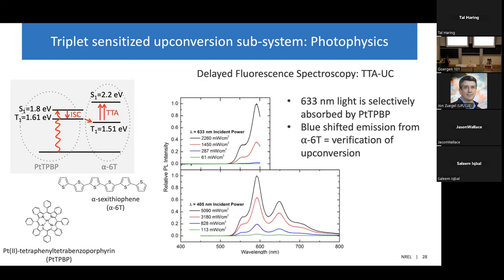All right. So after proving that we're populating the triplet levels of alpha-6T, we need to show that upconversion is actually happening. And for that, we turn to delayed fluorescence spectroscopy. So we photoexcited this mixed film at a wavelength that's selectively absorbed by the platinum porphyrin compound, 633 nanometers of light. And the emission is shown in the top panel here. And you'll notice that the emission from the system is actually coming at a shorter wavelength, or a higher energy, compared to the excitation. So that's a clear indication that upconversion has occurred. And then the spectral shape of the emission also matches that of the direct emission from alpha-6T. So we know that it's coming from the same species, in this case, the alpha-6T singlets.